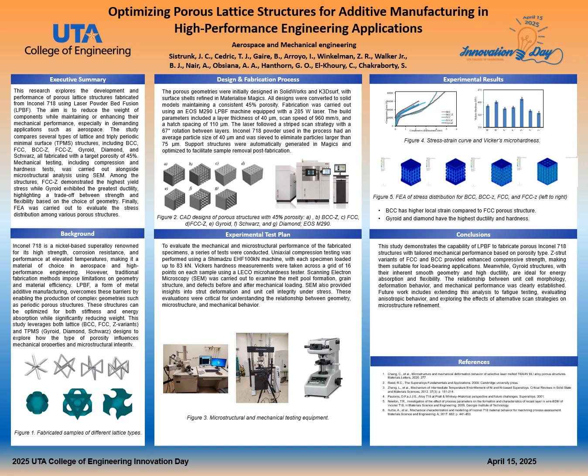Also, we did FEA analysis, and based on it, we saw the stress distribution for different porous structures, and we compared the values for stress concentration using different porous structures. We saw the FCC structure has less local strain than the BCC structures.